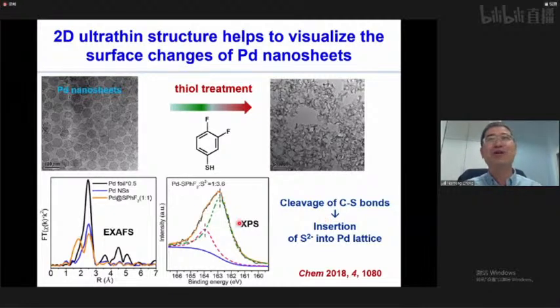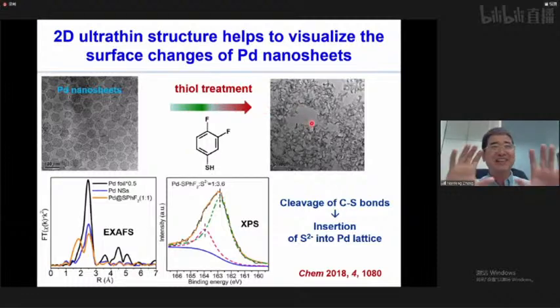Several years ago, actually, we had a totally unexpected result. Initially, we tried to modify the palladium surface with a thiol. So basically, we treat these palladium nanosheets. The thickness is only 5 atomic layers, because we made this material more than 10 years ago in our group. After treating, as you can see here, all these nanosheets, initially hexagonal, are highly distorted. So what's the reason for that?